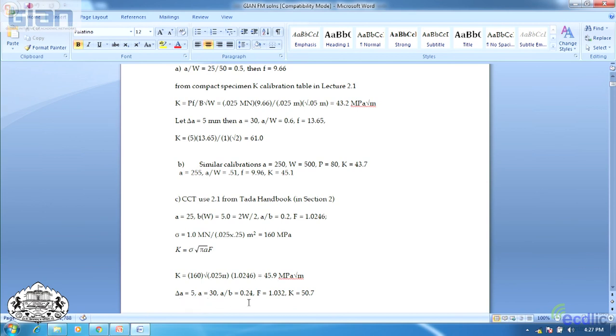Change the crack length by 5. A over B is 0.24. On that table, if you do linear interpolation, that's good enough. You don't need to do anything real fancy. So linear interpolation pretty much gets it. Then capital F goes to 1.032. That was my linear interpolation, and K went up to 50. So that's about 10% change. So that goes up in a medium amount.